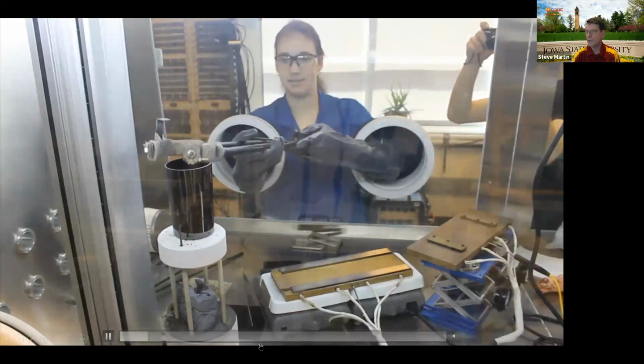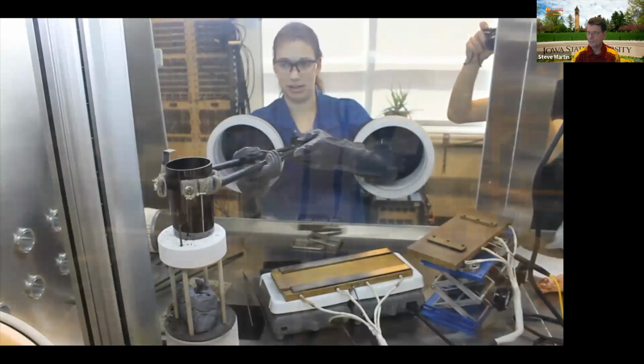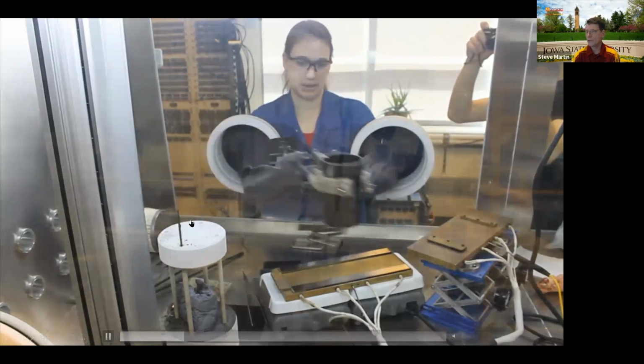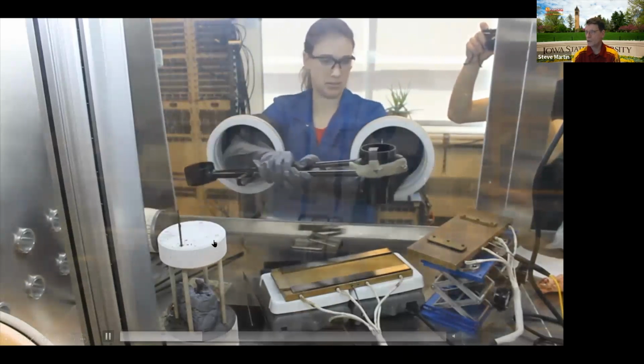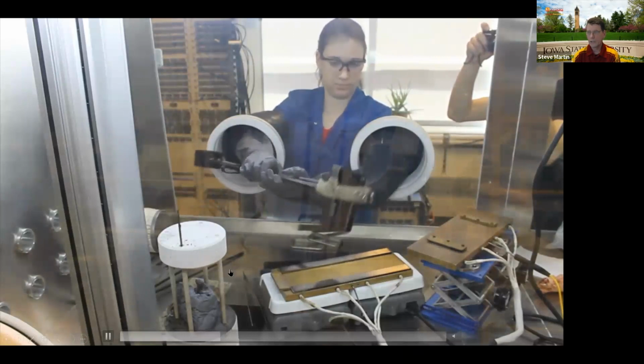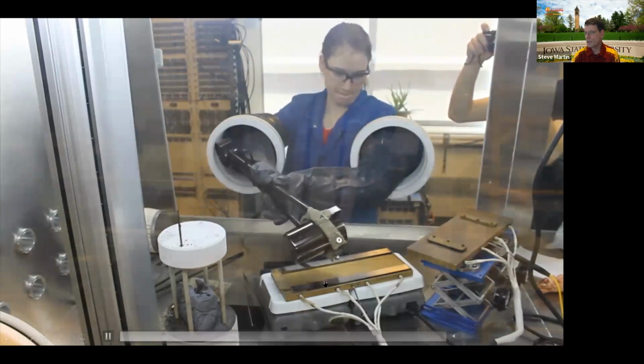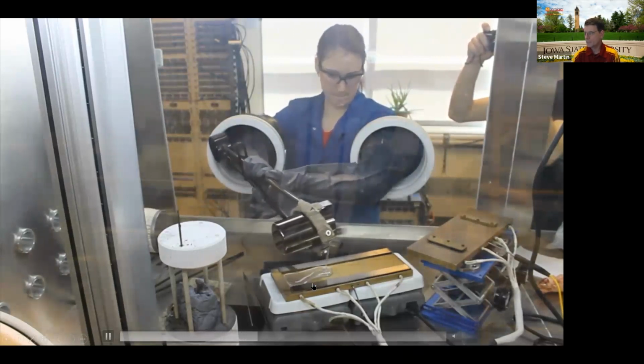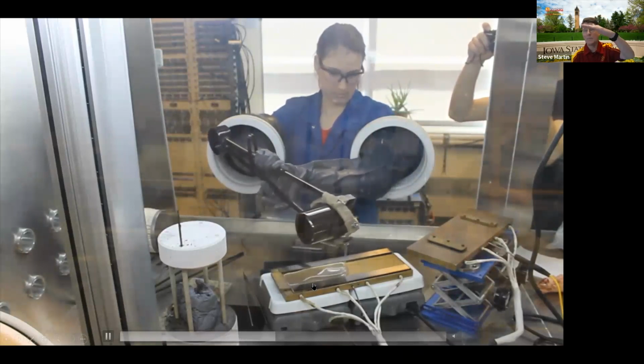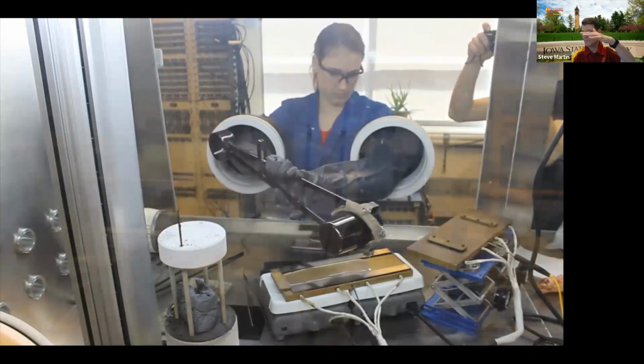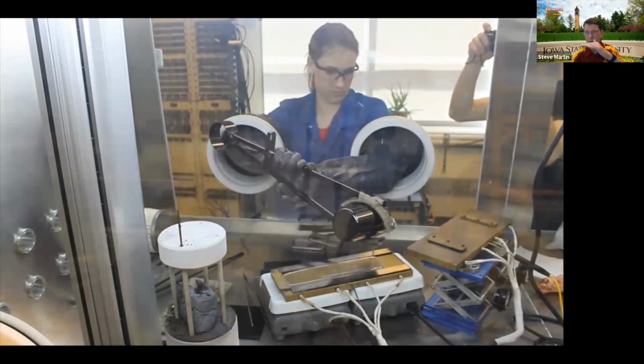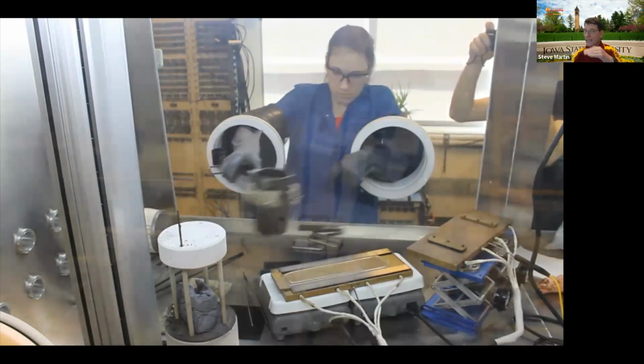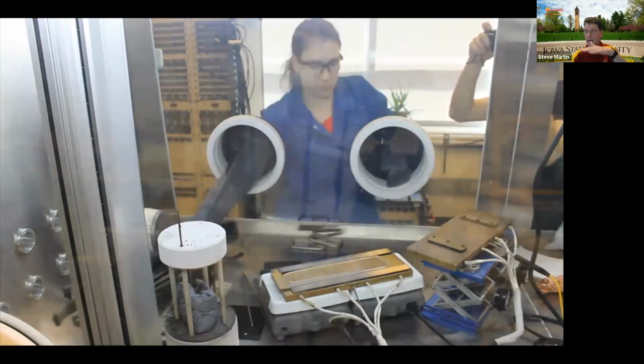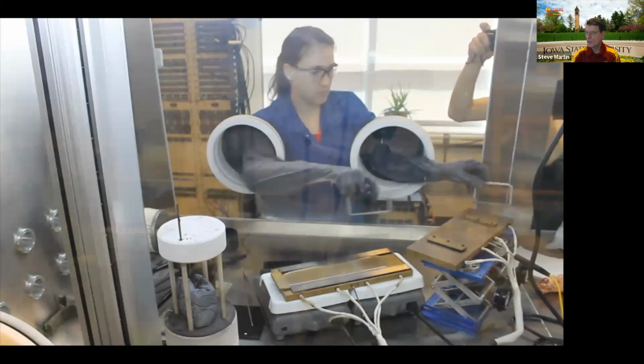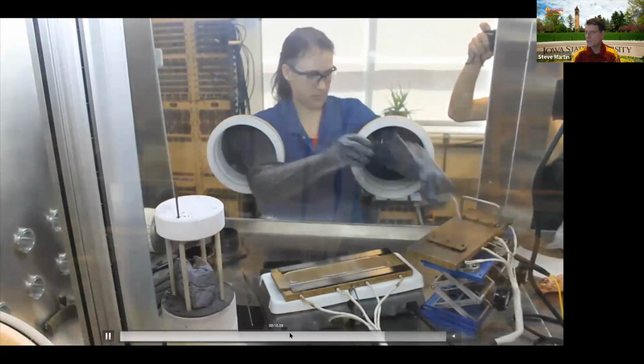This is a student of mine, Adriana. And she's lowered the furnace out, and you can see she's got a crucible full of glass, and she's swirling it around to make it uniform, and she's pouring that onto a hot plate. And that hot plate is just warming the glass up so all the glass comes to the same temperature, right below the actual softening point. We're going to heat it up higher than that, but to quench the glass, we need a bit lower than that. So then you can see the furnace raising back up again.